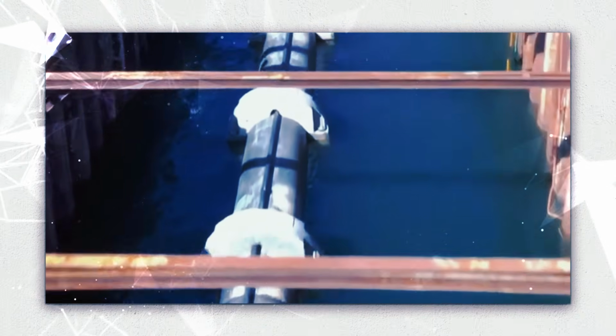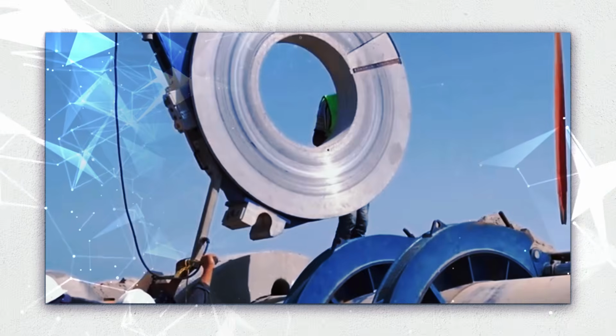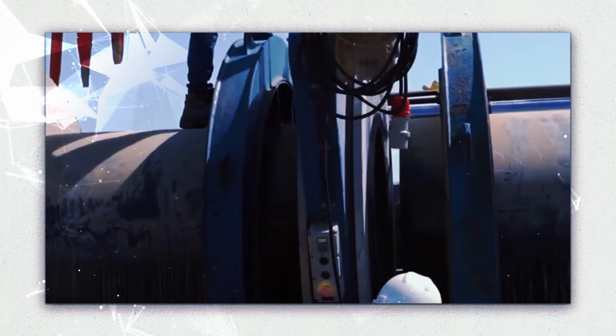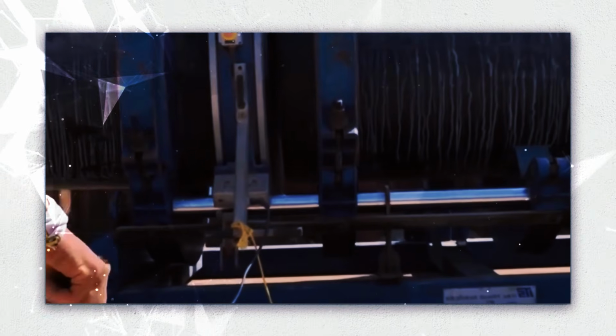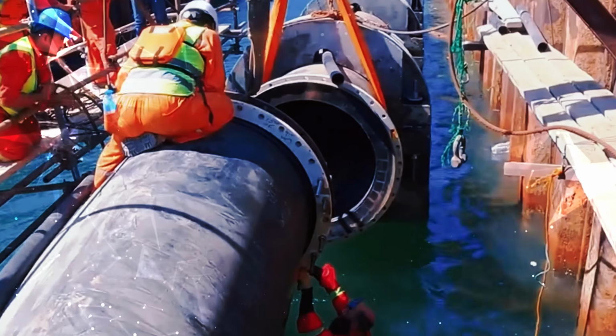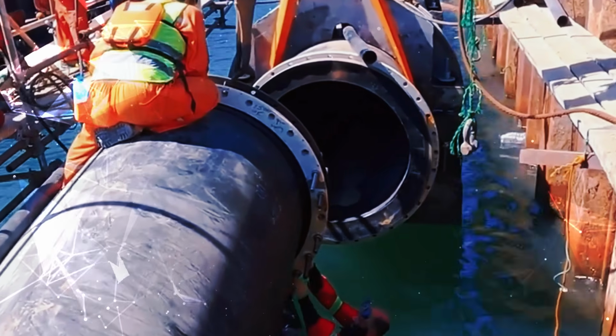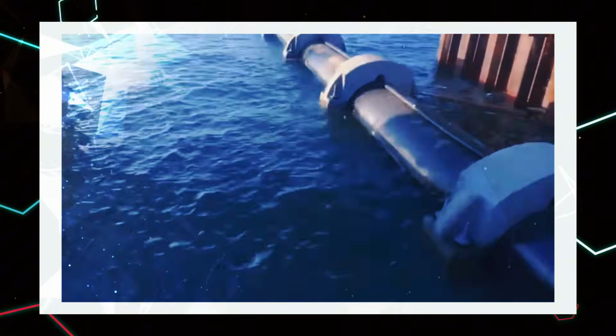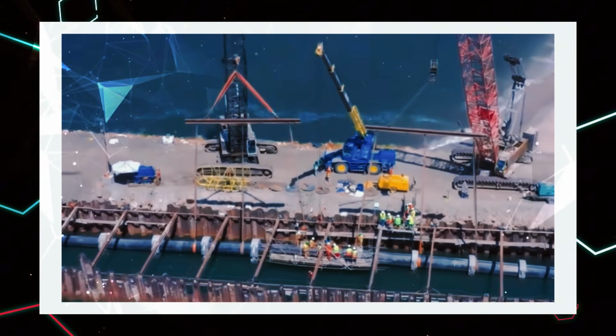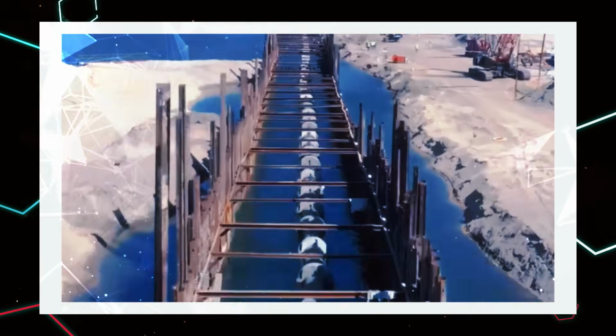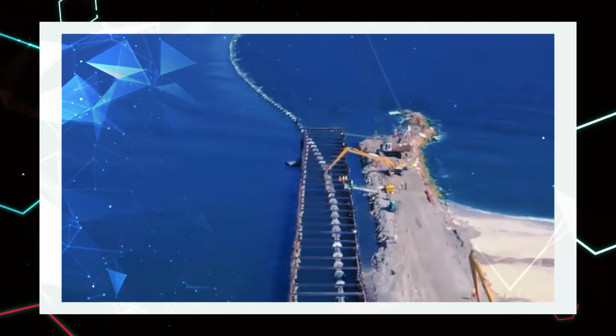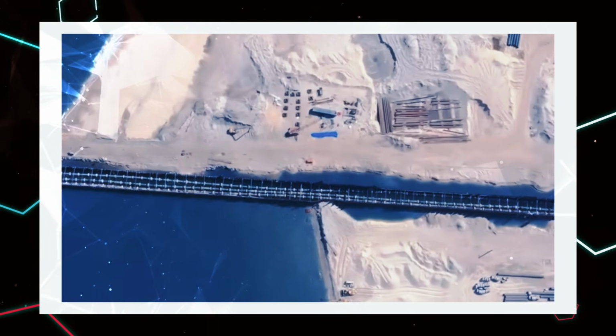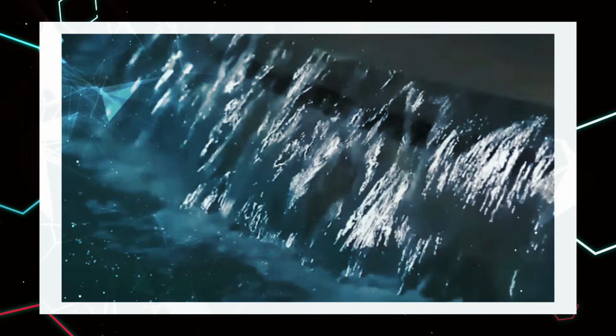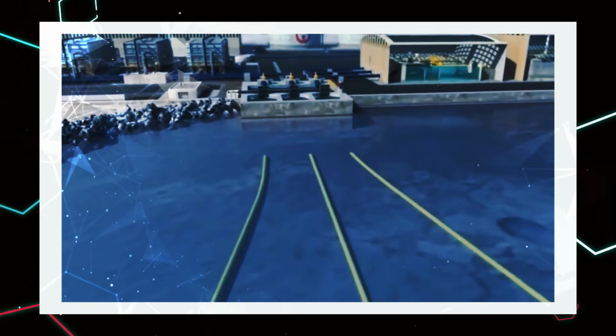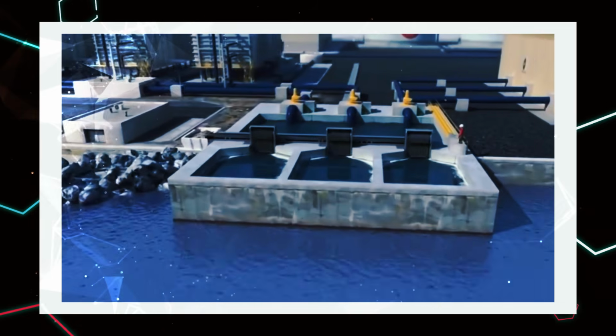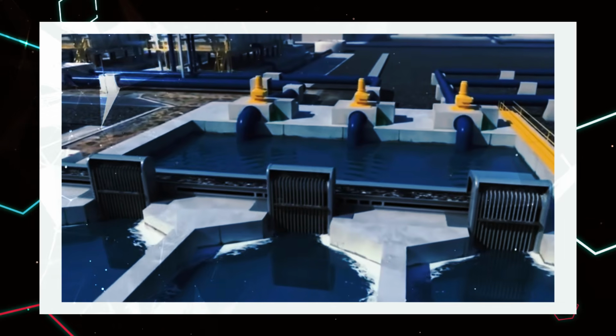At the welding site, an internal hydraulic alignment clamp is positioned inside the joint and expanded with 360-degree fixing shoes, keeping the two pipes perfectly concentric and aligned before and during welding. An automated welding operation, supported by a team of approximately 80 professionals and dozens of specialized machines, is capable of performing up to 150 welds per day on 42-inch diameter pipes, about 3.5 feet.